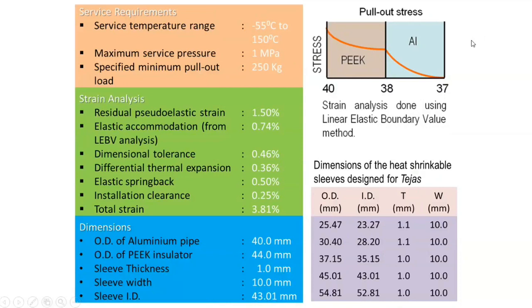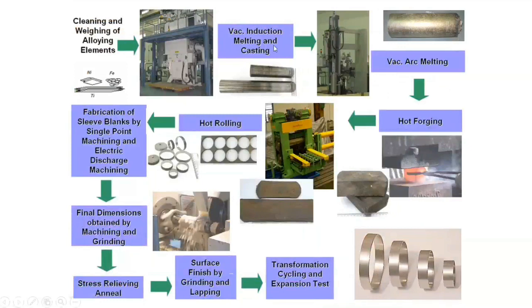You can work out the kind of stress that you need to apply, and therefore you know the width of the sleeve and the thickness of the sleeve, and you also know how much of the elastic strain this PEEK is actually accommodating. It's a very simple Lamé-type problem, and from that we can get the dimensions of this. Effectively, it's a sleeve which is smaller than the PEEK insulator, put in liquid nitrogen, expanded, put on top, and it recovers its original shape, and it still has 1.5% strain on that material, so that when you apply it in a condition even up to 150 degrees, you can twist, and up to the limits what it has been designed for, it can still hold out. So that is that application there.